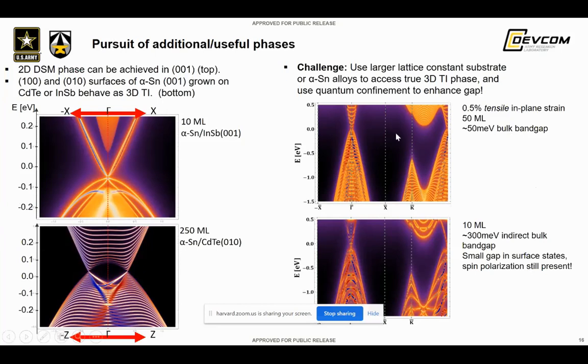You can actually do simulations using this technique, looking at materials that have a large lattice constant. And George showed that alpha-tin layers grown on a lattice constant that gives tensile in-plane strain, as opposed to compressive, can actually show a very nice formation of a 3D TI material, and that can be quantum confined and you can open it.